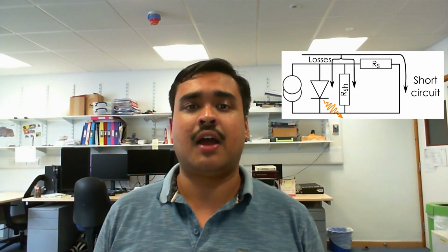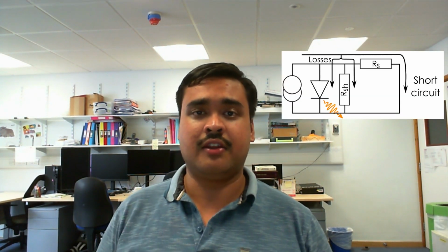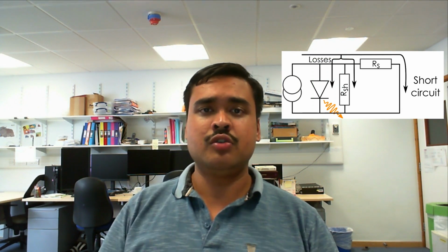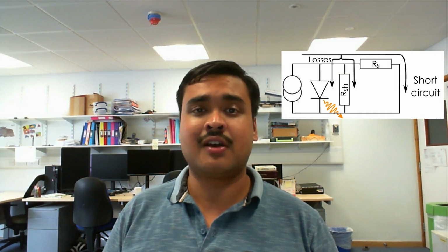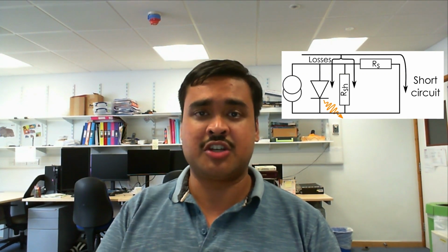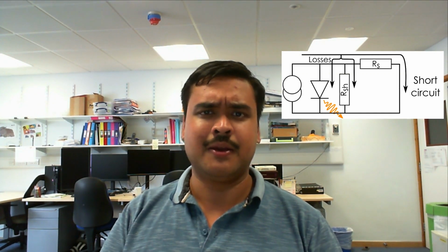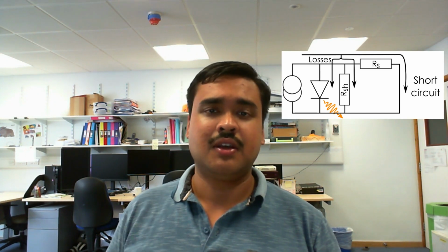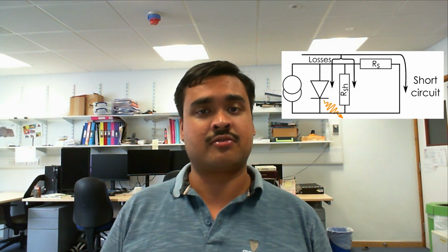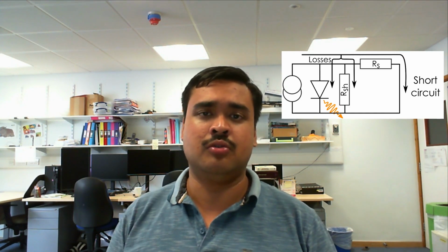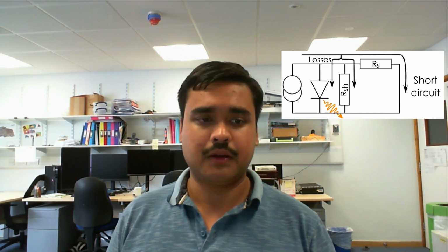Something we really did want to look at also was the photoluminescence at short circuit. See, when you have a solar cell and you connect it in short circuit, that is, you connect the leads together, you should have zero photoluminescence. This is because photoluminescence comes from electron-hole pairs generated in your solar cells recombining and releasing some light. Except at short circuit, all the charge that you've generated should be extracted and there should be nothing left to undergo photoluminescence.